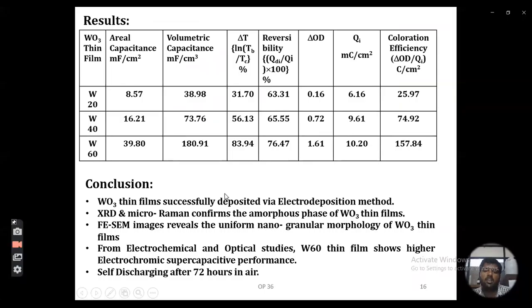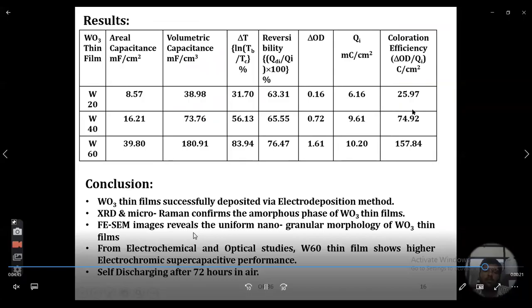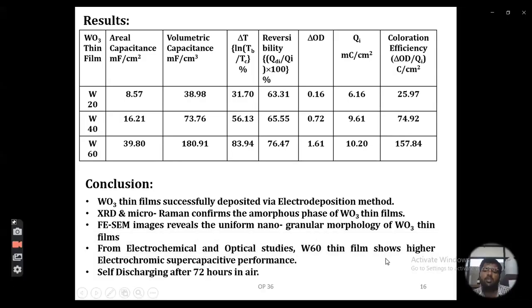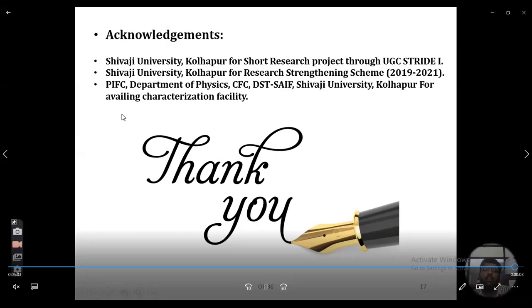And the conclusion is: the amorphous WO3 was synthesized using the electrodeposition method. XRD and Raman confirmed the amorphous nature. FESEM reveals the uniform nanogranular morphology of the WO3 thin film. From the electrochemical and optical study, it is clear that the W60 thin film shows higher electrochemical supercapacitive performance, with self-discharging after 72 hours in air. Then, acknowledgement to Shivaji University.